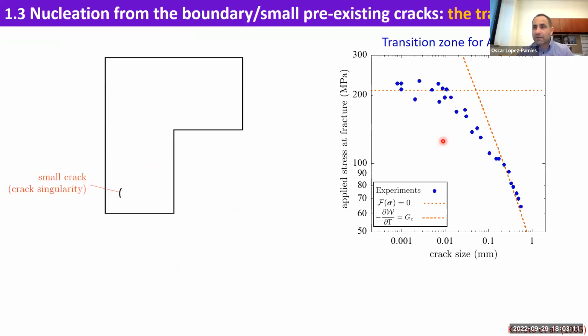And then, of course, you have the intermediate region, and this is also well known from experiments. This is experiments on alumina, which is a ceramic. And so these experiments were done on a specimen where you have a pre-existing crack, and you see here the crack size. If the crack is big enough, the critical value of the load that you apply at which the crack goes is controlled by Griffith. Griffith is this diagonal line. As you make the crack smaller, right? This is an initial crack. You make many specimens with smaller and smaller cracks. You see that you have a transition from Griffith to strength. Strength is the horizontal line.